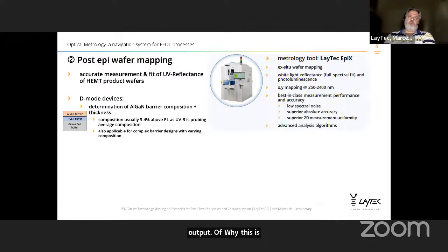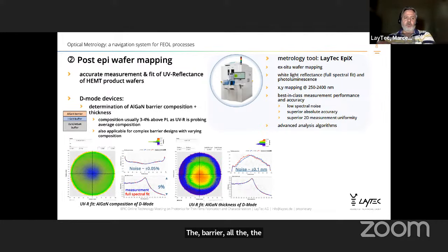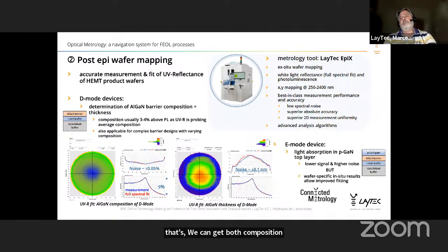Because if you're looking either at D-mode and then also at E-mode devices, you want to determine very accurately the AlGaN barrier composition and thickness, and this is usually done with photoluminescence, which is not as accurate as our reflectance measurement, because the reflectance measurement is measuring the whole of the AlGaN barrier. So if we do a UV reflectance fit, we can get both the composition and the thickness. And similar results we can also get on the E-mode devices.